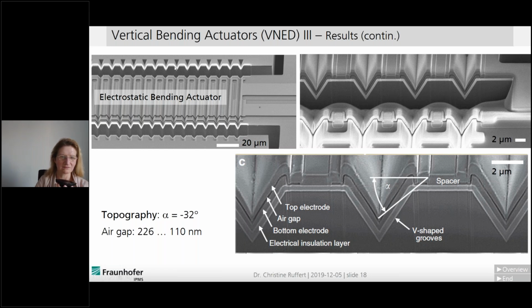And you see on the top, on the left-hand side, a section of about 20 micrometers. And you see an enlargement on the right-hand side, and you might see the single layers. And on the bottom, they are indicated. So you see the top electrode, which has a thickness of 500 nanometer in this case. And this is made of titanium aluminide. And then you see the air gap, and the air gap is written on the left-hand side. This is about 200 nanometer in this design, so very small.